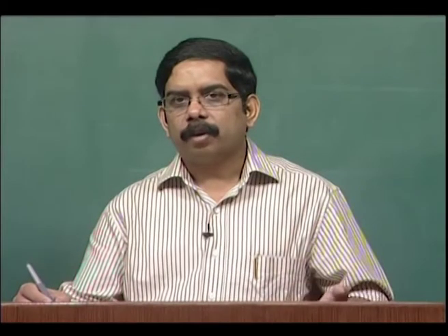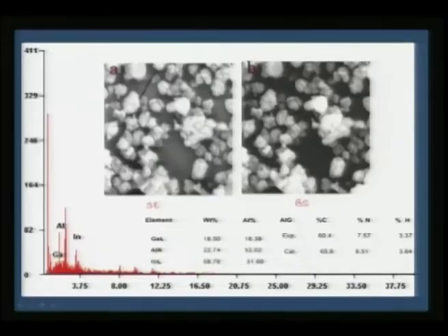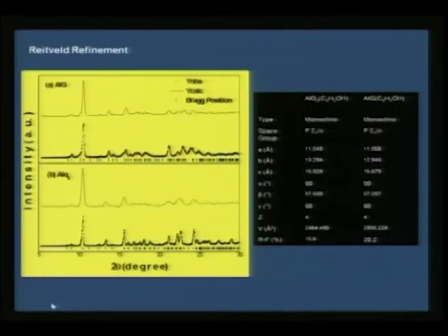In black and grey resolution they will all be in different shades, but what you see here, from this picture to this picture, almost the color contrast is exactly the same. Therefore this is not a mixture of 3 complexes, but this is a solid solution, and because it is a solid solution, the stoichiometry at this point is going to be the same as at this point. The stoichiometry in any given place will be the same, and that is the simple definition of a solid solution.